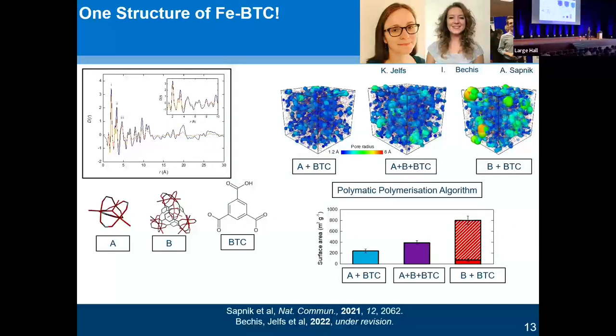So after confirming those building units are present in our amorphous equivalent, we then turn to computational help through this Polymatic polymerization algorithm. I'm not going to say that one again. And this is essentially connecting things and making a polymer. It's originally used for organic polymer structure prediction. We can combine these different blocks and different models. So for example, just taking the trimer and BTC produces an amorphous model with a low surface area. Combining the supertetrahedra with BTC produces a model with relatively high surface area, although most of it is inaccessible. And it's only when you mix the two in 50% equivalence, you form an amorphous system with some trimers, some supertetrahedra, do you get something which resembles your experimental result?